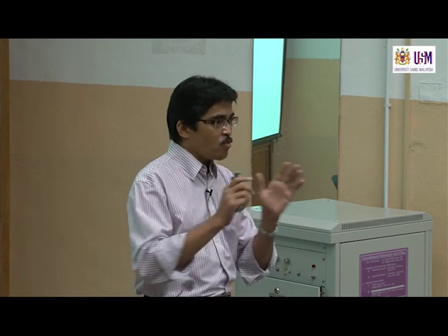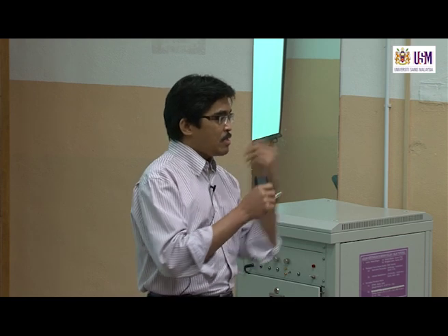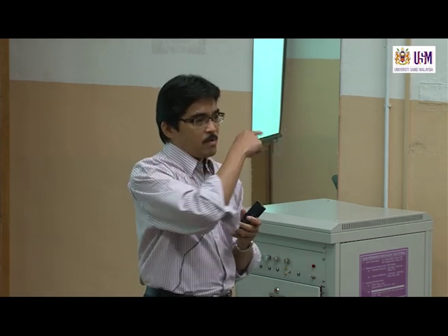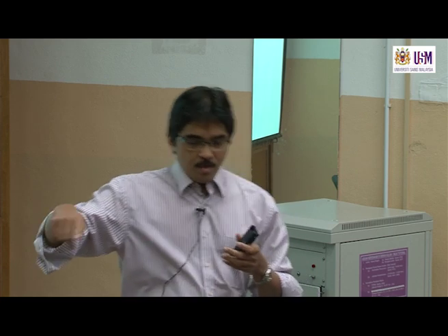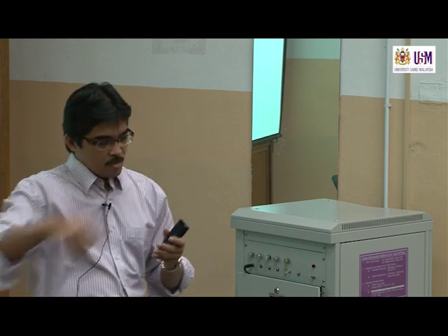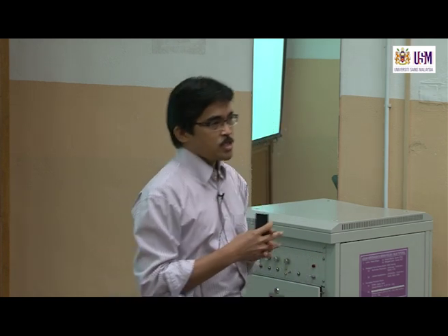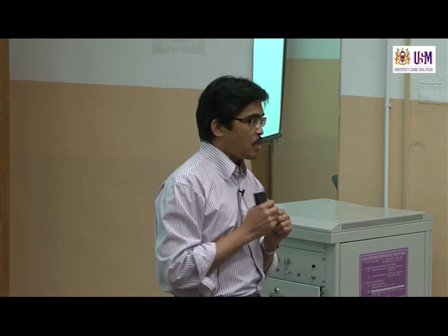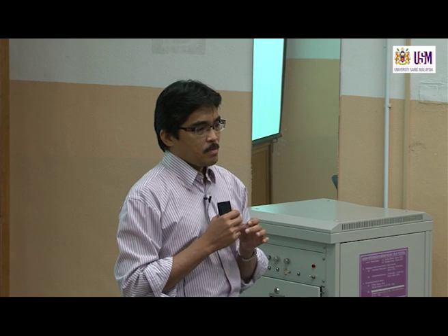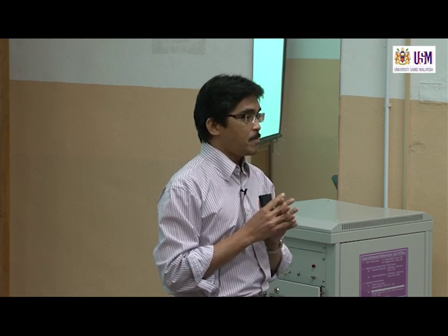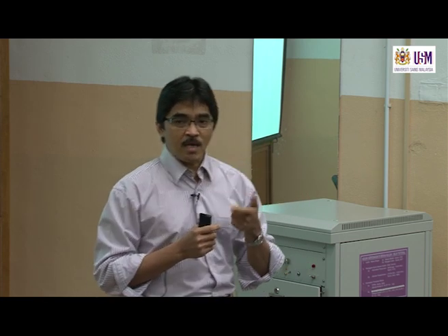How do we know? In the previous lecture, we said we can look under the microscope, where there is no more Maltese cross, or in the DSC instrument, we can see the complete peak from the onset to the end. So we can see the whole peak. That's how we can determine complete gelatinization. So to get complete gelatinization, we need more than 60% water, we heat above the gelatinization temperature, and we give sufficient time. So it is a combination of temperature, time, and water.